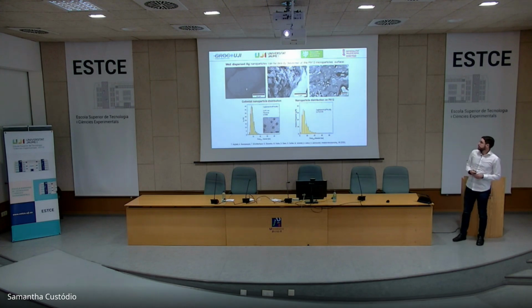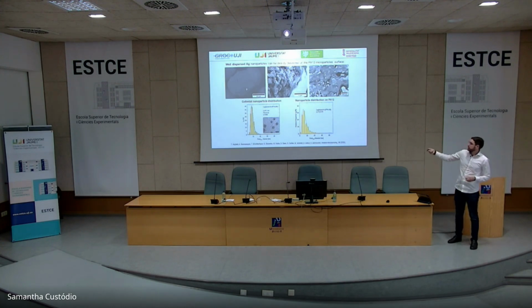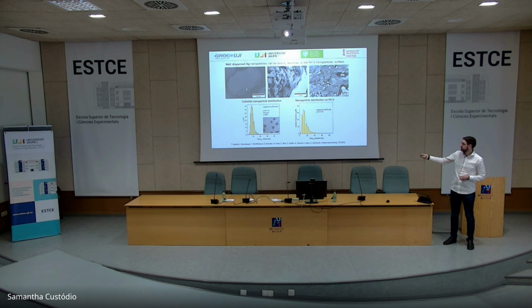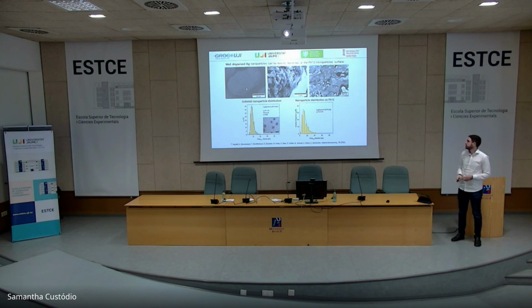Here you see some pictures. It's quite nice when we do this with polymers. We have done it also with metals, but the point is when we do SEM, the silver has quite high contrast and the polymer much lower. So all these bright spots are the silver nanoparticles supported on the surface of these nylon microparticles. If we measure the size of the nanoparticles on the surface, it's pretty similar to the initial one, maybe just a small enlargement, but it's common.